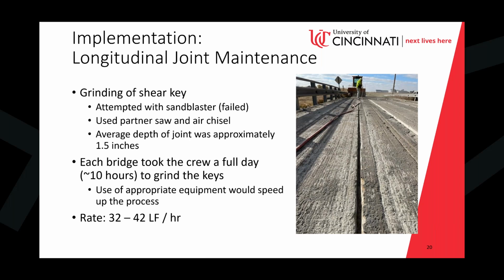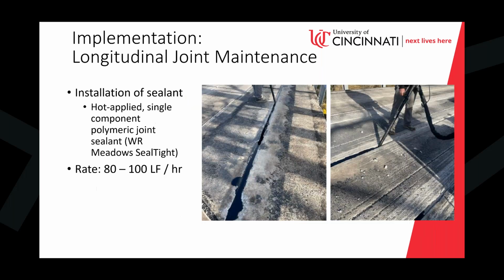It took their crew a full day, about 10 hours, to grind out the keys, which ended up being a rate of about 32 to 42 linear feet per hour to grind out the shear key. Use of appropriate equipment would speed up the process. Using some kind of walk-behind crack routing machine would have been probably a quicker and easier option here. Then they installed a sealant, a hot applied single component polymeric joint sealant. It's called Seal Tight. This could be done at about twice the rate of the grinding process.